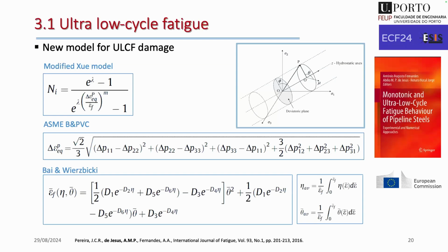Then we make some post-processing using this uncoupled model just to try to anticipate the crack initiation. So we used the Xue model, which was developed at the time for just uniaxial loading, and then we extended it for multi-axial loading using the ASME boiler and pressure vessel code formula for the equivalent plastic strain range. This equivalent plastic strain range appears already in the Coffin-Manson, but we normalized it by the fracture strain of the material. That means the strain range effect will be more or less damaging depending on how far or near we are from the ductile fracture of the material.